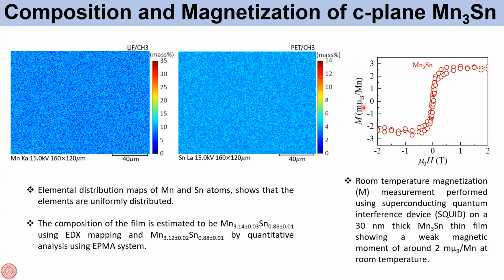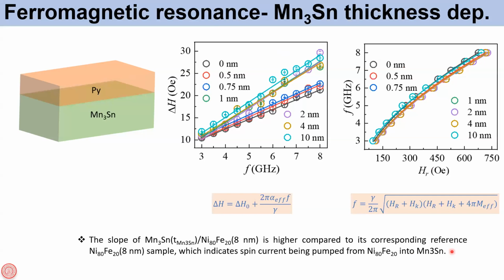This weak magnetic moment comes from the fact that the magnetic moments are a little bit tilted out of plane. So it behaves like a very weak ferromagnet, although this is an antiferromagnet as such. But this magnetic moment is really small. And then we deposited permalloy on top of that, and then did FMR and inverse spin Hall effect